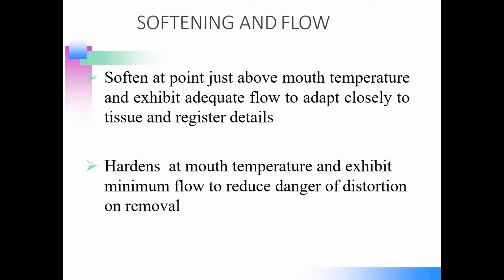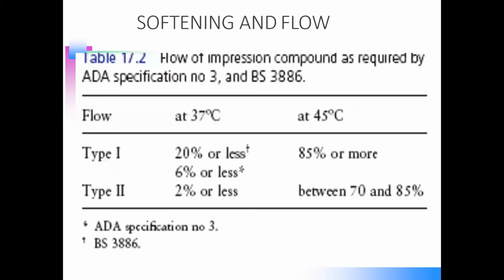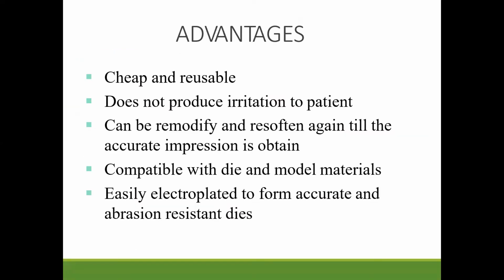Below this temperature, whenever it comes in contact with the mouth temperature, which is 37 degrees Celsius, it will get completely hardened. So, as per ADA specification number 3, the flow of type 1 impression compound at 37 degrees Celsius should be 20% or less, while at 45 degrees Celsius, it should flow more, that is 85% or more. So coming on to advantages, it is cheap and reusable.